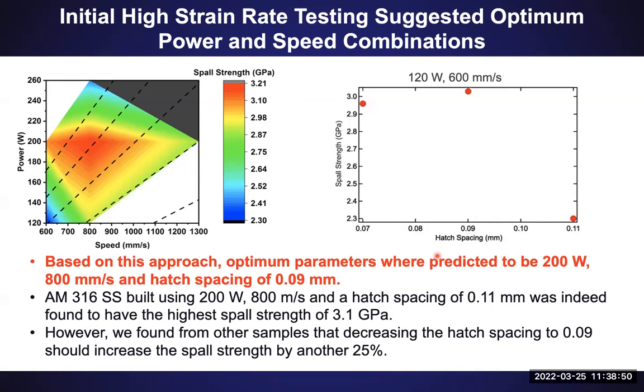So we basically looked at 9 samples, and here is a plot where we plot laser power as a function of laser speed, and I color it by Spall Strength. You can see that out of all the samples that we had, there is a region in the center of this plot where there was a combination of laser power and laser speed that led to the highest Spall Strength that we could measure in these experiments, which was about 3.2 GPa.